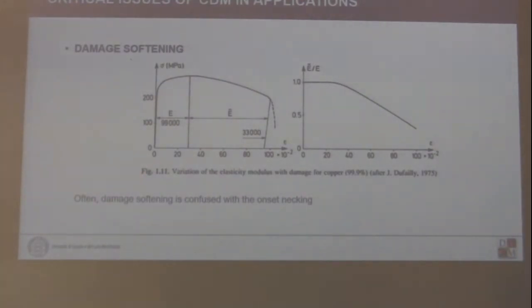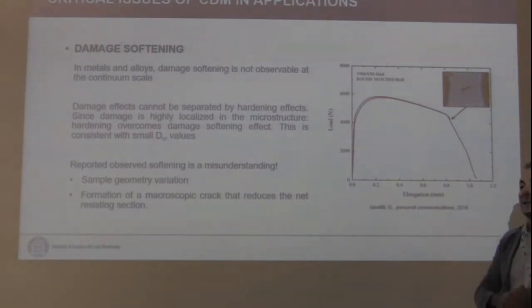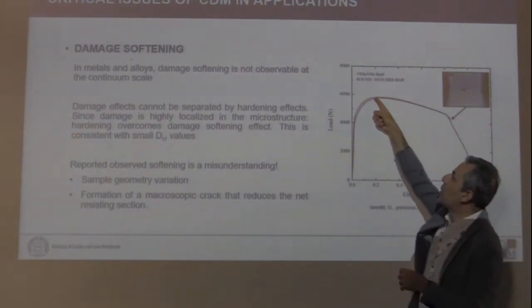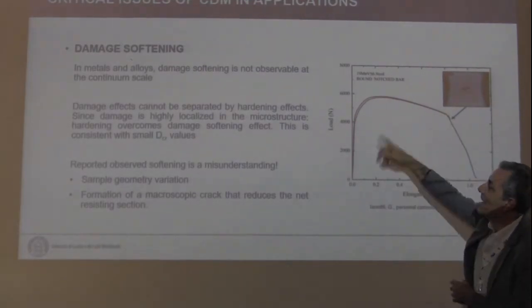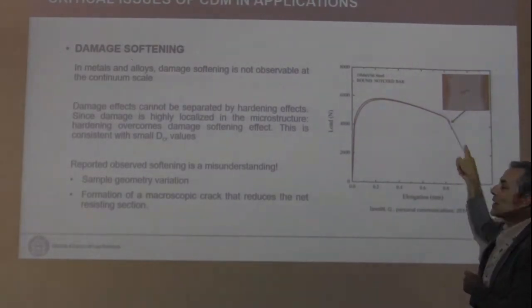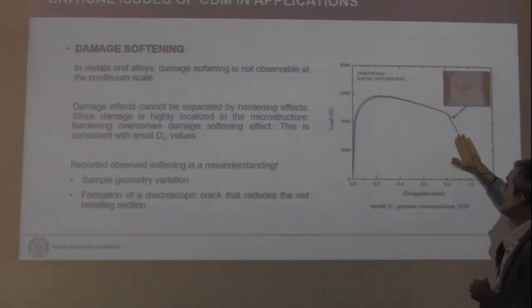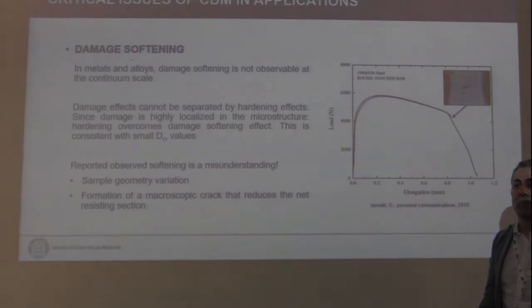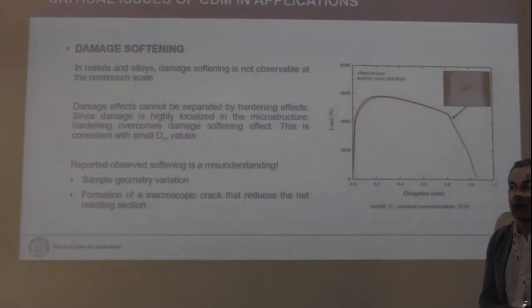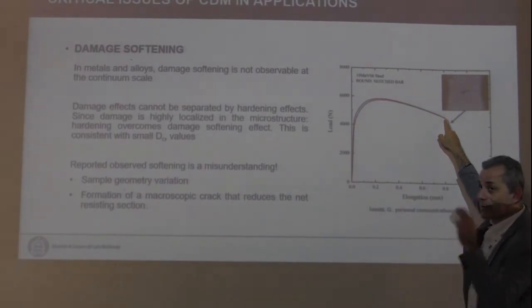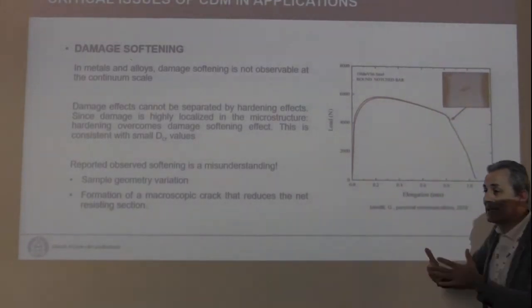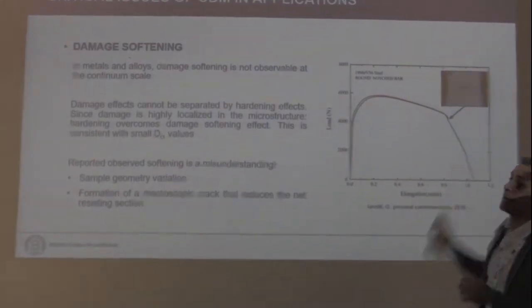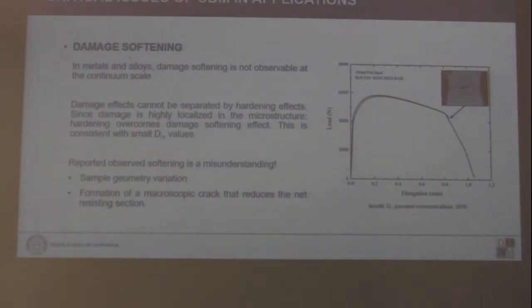And later other people, also in the French school, said, okay, now this is not the initiation of damage, but damage initiation in a tensile test is when we start to see this change in slope. We proved that this part of the curve is just an artifact from the test that comes from the stiffness of your machine, and already here, as soon as you stop the test at this point, you cut the sample and you open up the minimum section, you find out there is already a macroscopic crack. So it means that once again, softening cannot be measured at the macroscopic scale, as the damage effects cannot be measured at the macroscopic scale.